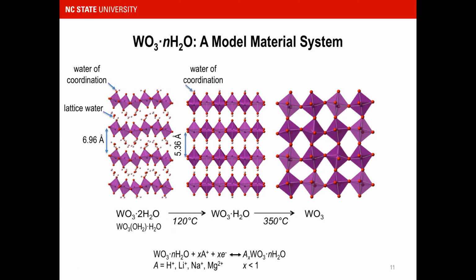And now what we have is a system where we can control the amount of water in the structure at low enough temperatures where we're not changing the surface area or morphology of our particles. And these are powdered materials upon synthesis. All 3 of these phases are electrochemically active, meaning that they will intercalate a variety of cations from the electrolyte. All of them are based on the redox of tungsten 6+ to tungsten 5+. So that's all staying the same too.